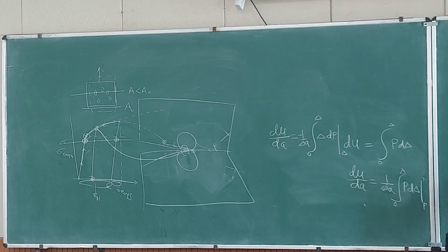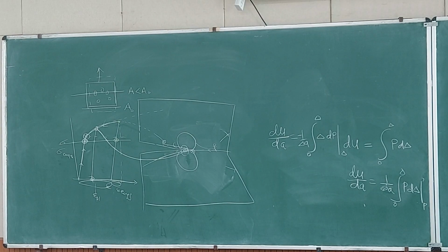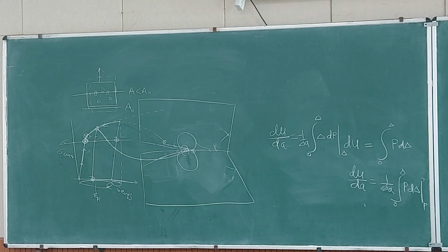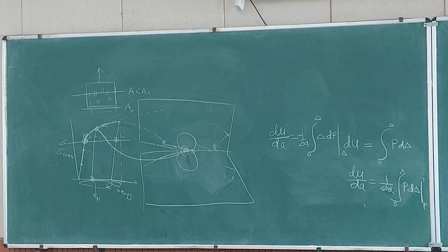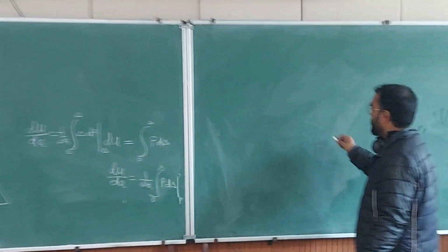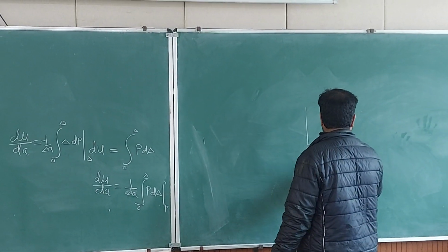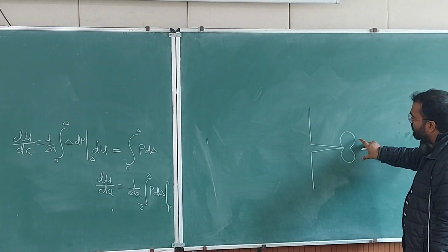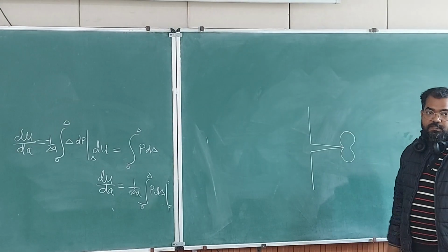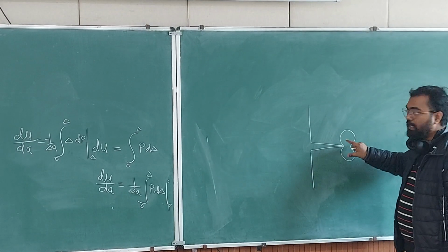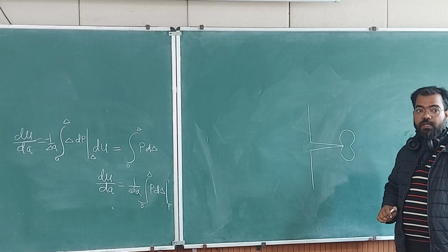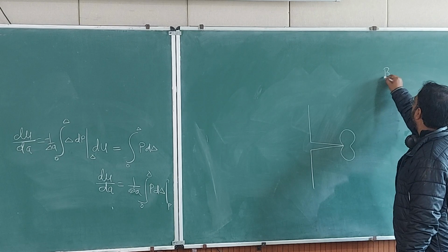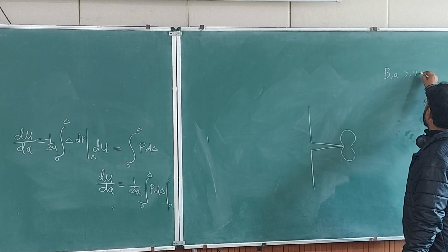And because this theory is good in plasticity, when we assume it to be non-linear elastic, then it is valid inside the plastic zone also. Okay? Because we are following both. So we have one equation for stress strain, and that is valid inside the plastic zone also. Okay? So now if you conduct an experiment, you don't need to fulfill this criteria.